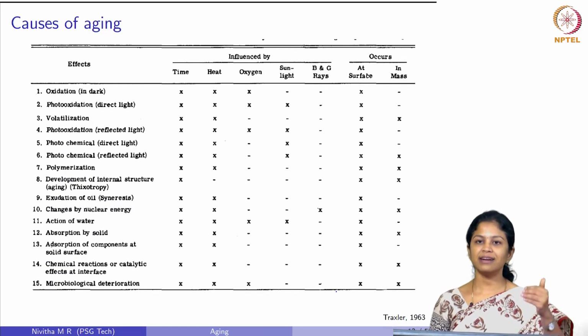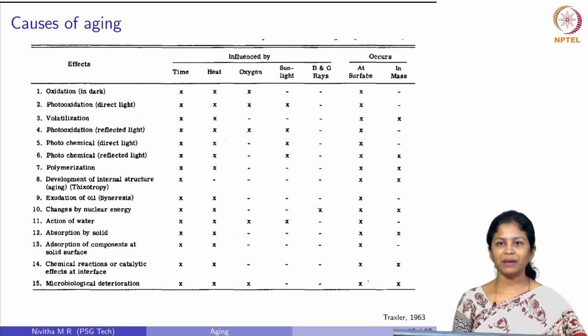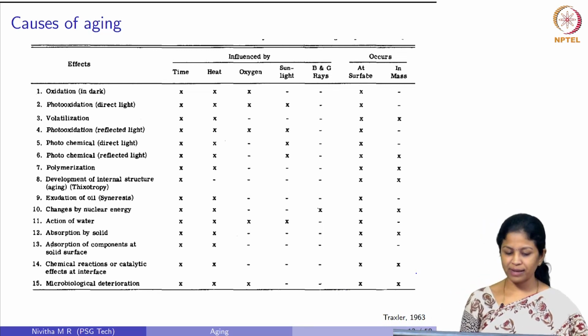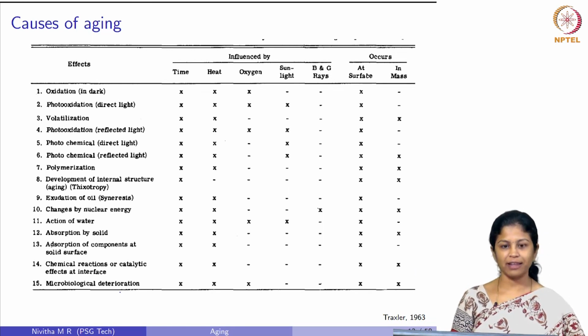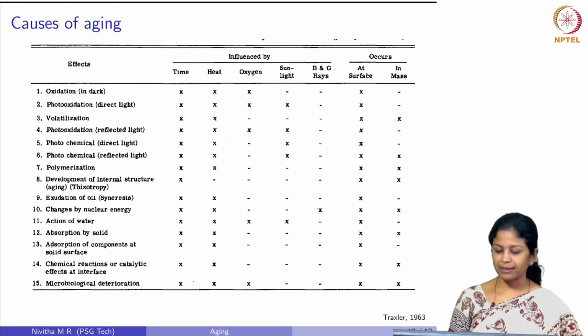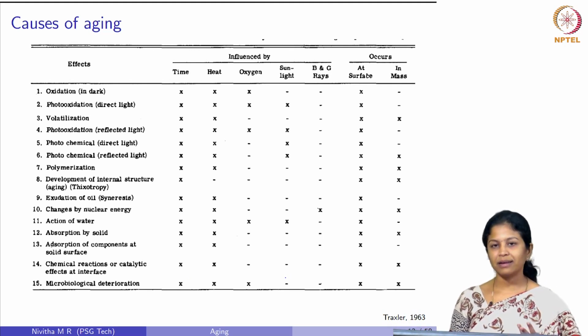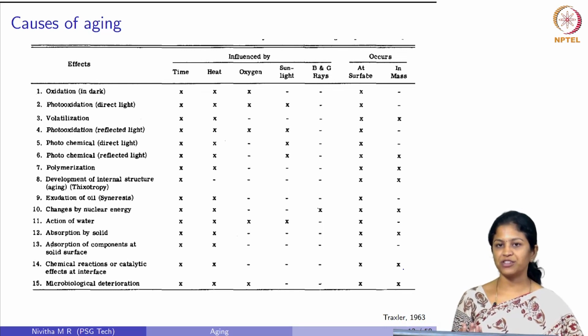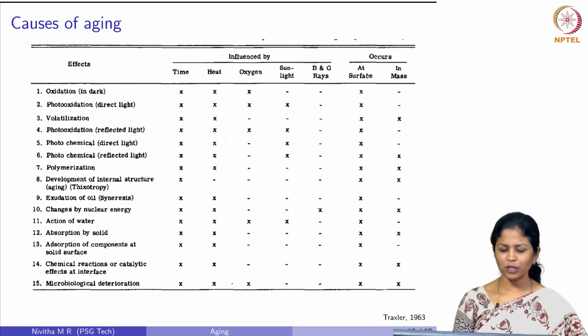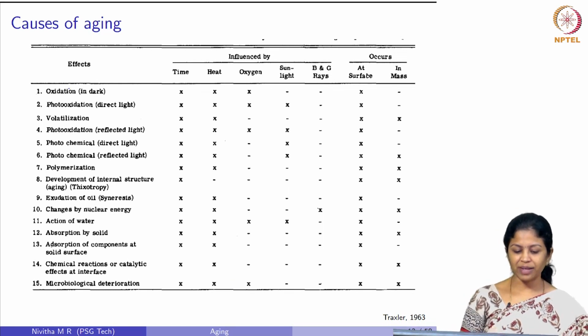So, Traxler has listed a number of factors which are responsible for chemical aging in bitumen. You can see this table here, there are about 15 factors which are listed here, he calls them effects, and each of these factors can be influenced by a number of parameters. So, what are these parameters that are listed here? One is time, second one is heat, oxygen, availability of sunlight and beta and gamma rays. And he has also said because of each of these effects, where does the aging occur? Some factors will cause aging only on the surface of bitumen, whereas some factors will cause aging in the entire mass. So, that is also listed in this particular table. The first effect is oxidation.